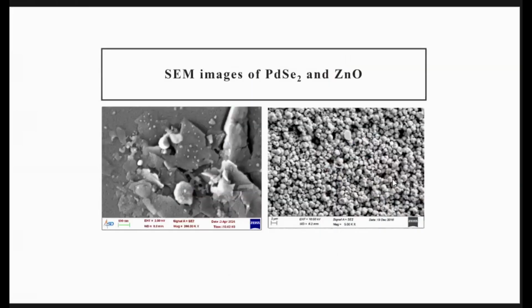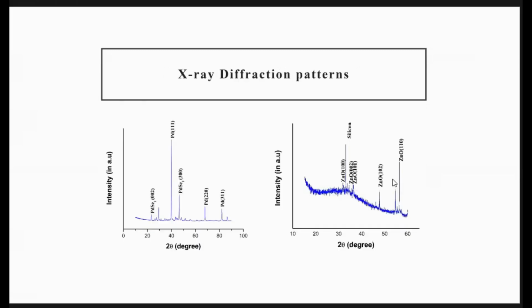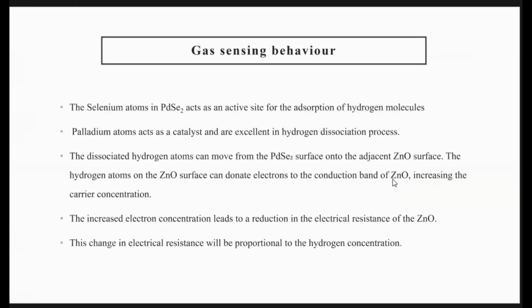And this is the same image we got for palladium. It is like a flake, palladium selenide flake, and zinc oxide will be like a nanosphere. So this is the XRD data. In the XRD data, it is seen that not only palladium selenide is formed, some palladium is also there. And zinc oxide and a silicon peak are there, since it is coated on silicon.